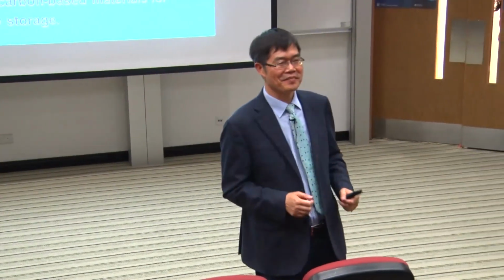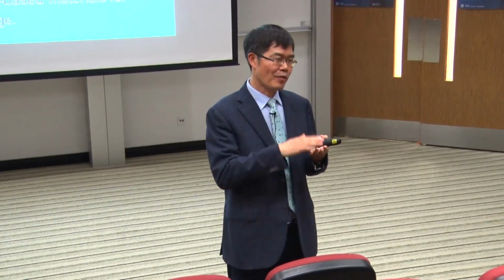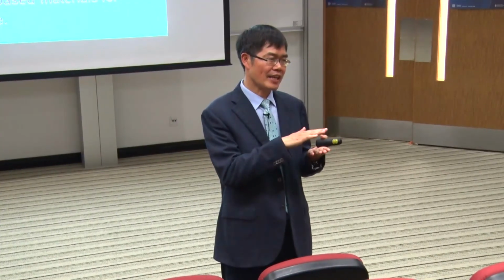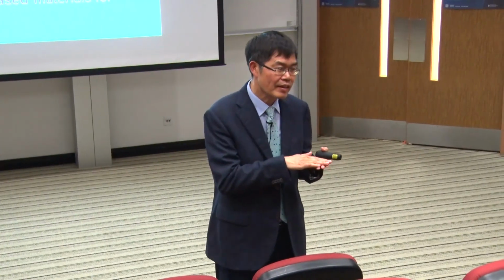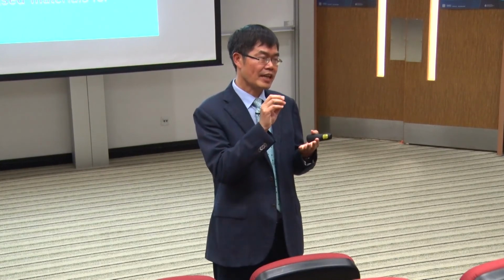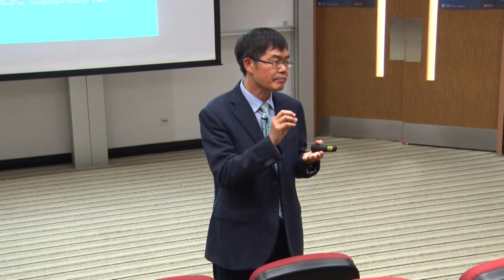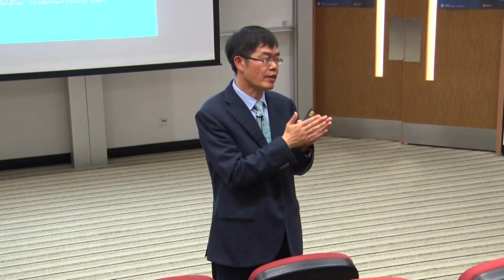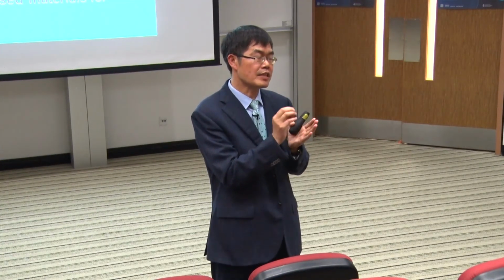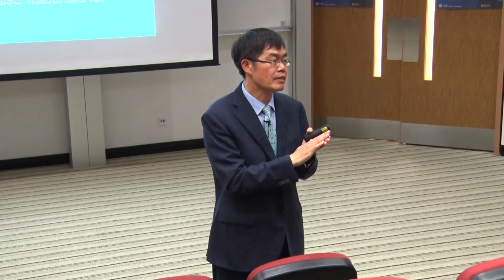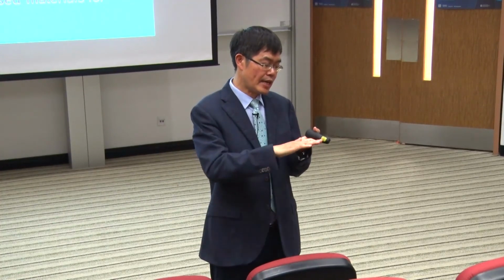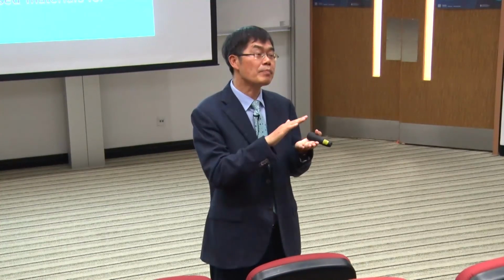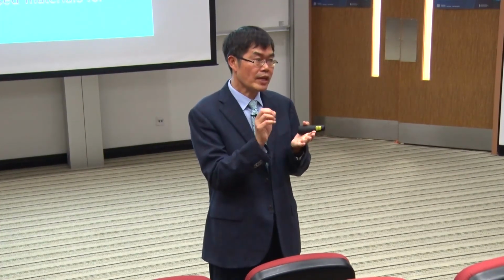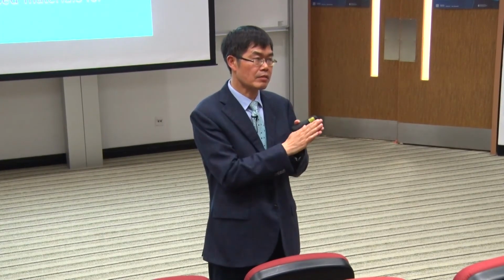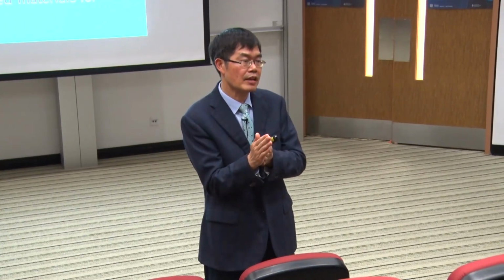Yes, it's very good. Theoretically, you're right. If we put something directly on the metal surface, the electric conductivity should be better, right? But considering the energy material, the active energy material is particles, and there is very poor adhesion between the metal current collector and the active materials. And also, because they are particles, the contacting area is not 100%. So if we put a very thin graphene layer, or some people also use carbon nanotube layers, we can control the adhesion between the metal current collector and the graphene suspension.